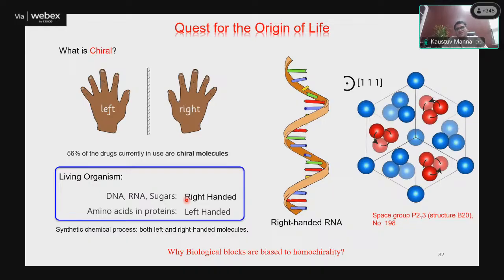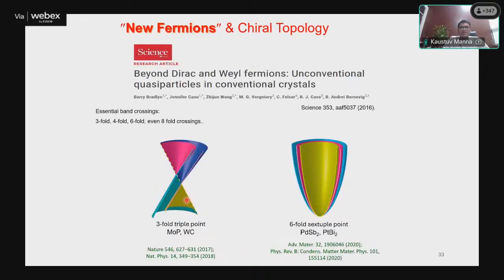So this is the quest for the origin of life, and we are trying to understand some part of this with respect to the chiral molecule, because now in momentum space we have the option that we can control these topological states with the structural chirality of this molecule. Everything, as I said, the symmetry is the most important part here. If you manipulate the crystal symmetry, the topological states are also automatically changed. We have shown in many papers, in my papers, that if you go from a right-handed chiral molecule to a left-handed chiral one, your topological states simply change. And this is experimentally observed.